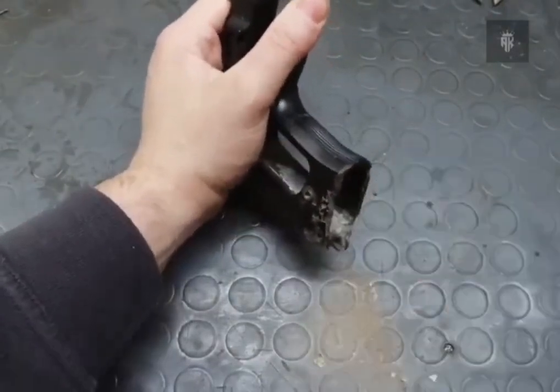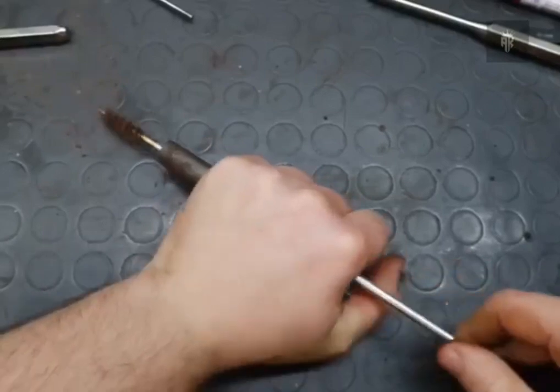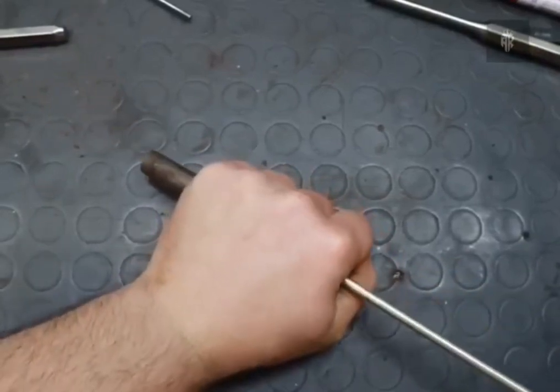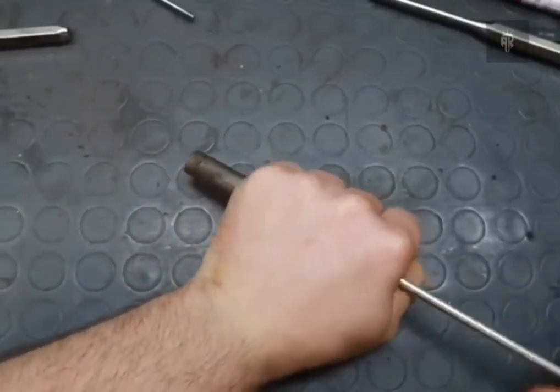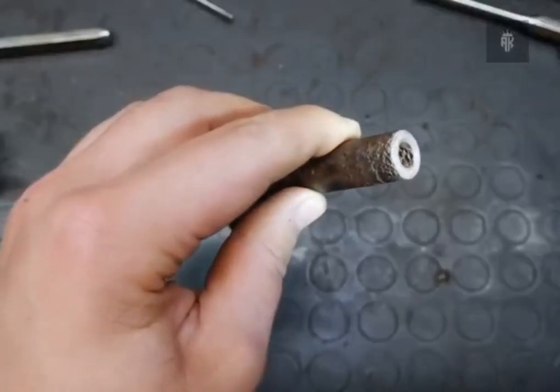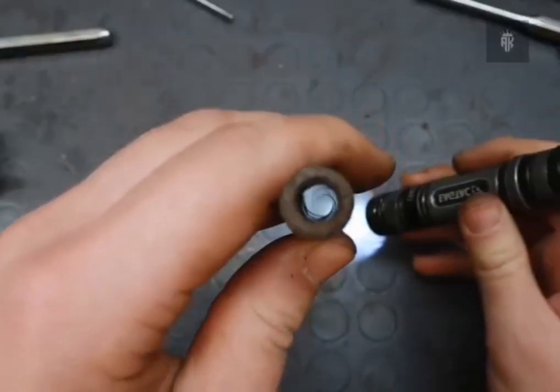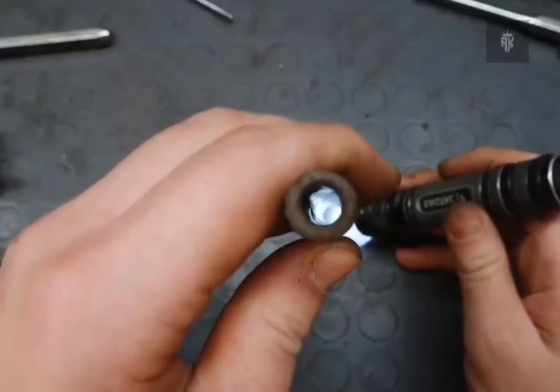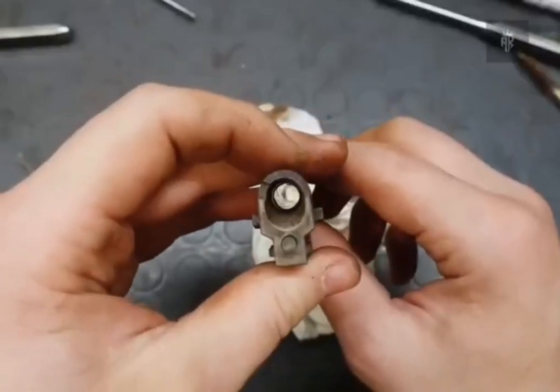Now, before reassembling the gun, let's look at the condition of the bore. Seeing a puff of red dust coming out while brushing a barrel is not exactly a good sign. However, there's corrosion damage only near the muzzle, while the rest is pretty much untouched, being less exposed to our four-legged friends. Overall, this barrel is safe to shoot.